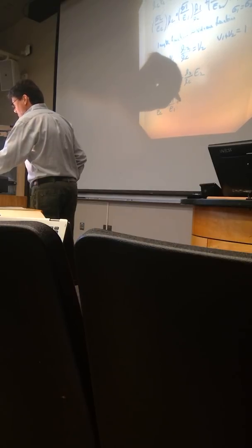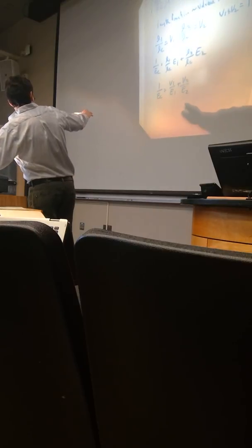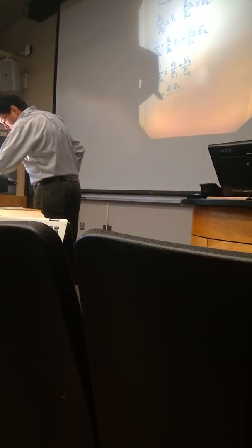Therefore, if you put that in terms of volume fractions, 1 over E of the composite is equal to V1 over E1 plus volume fraction of 2 over E2. You can rearrange that and have E of the composite equal to E1 times E2 divided by V1 times E2 plus volume fraction of 2 times E1. And now if you plot that,